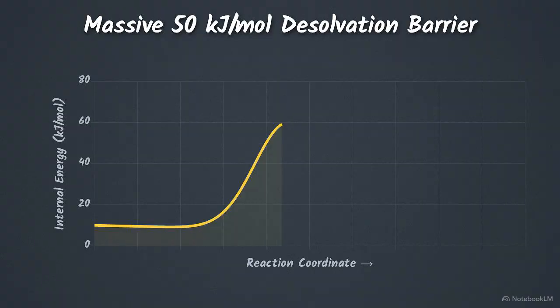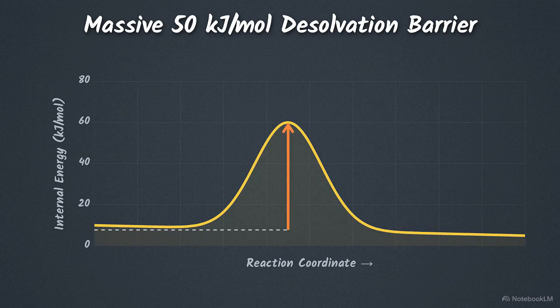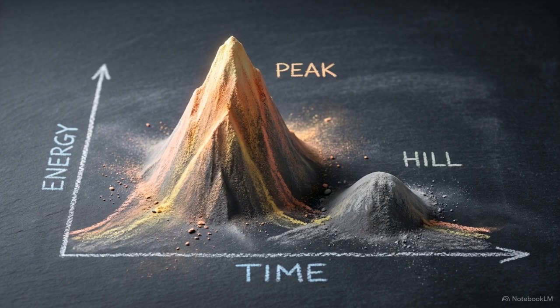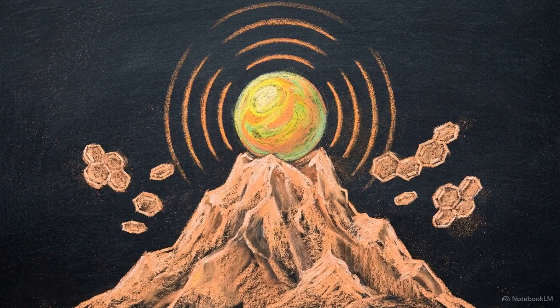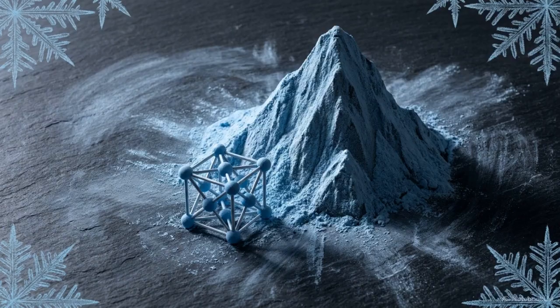This energy landscape chart illustrates the cost of that process. Stripping the shell requires a massive activation energy of roughly 50 kilojoules per mole. This dwarfs the 20 kilojoules per mole required to simply migrate through the SEI layer itself. At room temperature, the system possesses enough ambient thermal energy to overcome this 50 kilojoule barrier. The shell strips off easily. But at -40 degrees, that thermal energy vanishes.